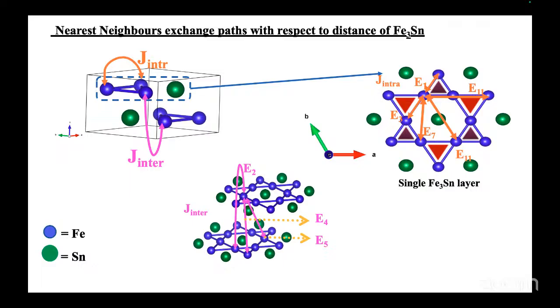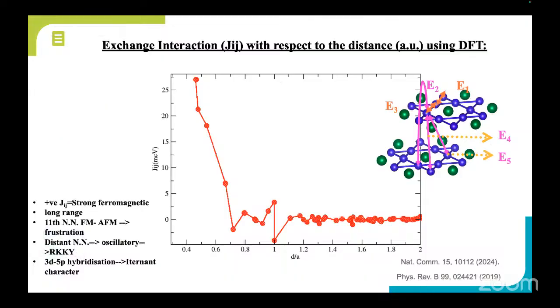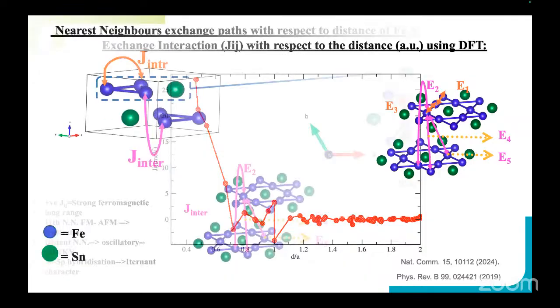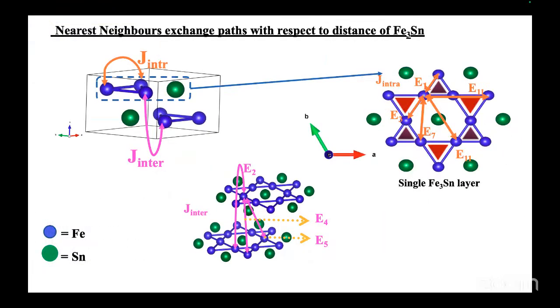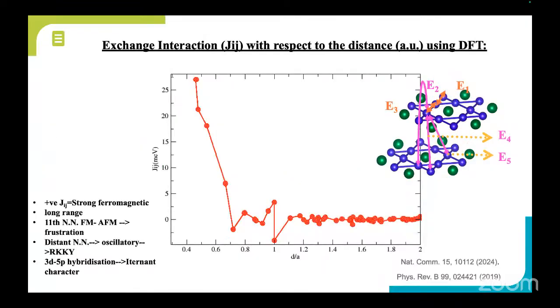After this, this is the plot for the Jij versus the distance. And here we can see that we get a very strong positive value. The first corresponds to the exchange value for the first nearest neighbor interaction, then second, third, and fourth. So from the first four, we clearly see a strong ferromagnetic coupling in the system, and it is quite long-range. On the 11th neighbor interaction, we see two points: one comes out to be ferromagnetic and another comes out to be antiferromagnetic.